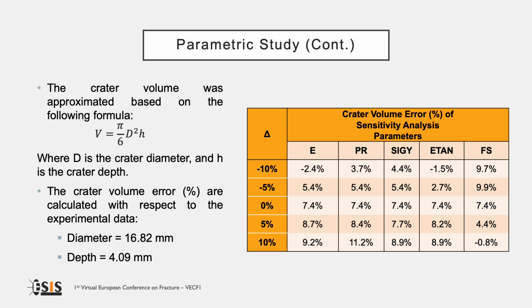The same results are here reported in a table. If we consider the baseline set of input parameters, the error is 7%. If we take into consideration the elastic modulus, the Poisson ratio, the yield strength, or the tangent modulus, we obtain the least error by decreasing this input parameter by 10%. On the other hand, if we consider the failure strain, we obtain the least error by increasing the parameter by 10%. This is also the configuration with the least error, which is lower than 1%. On the other hand, the highest error is obtained by increasing the Poisson ratio by 10%, obtaining an error of 11%.